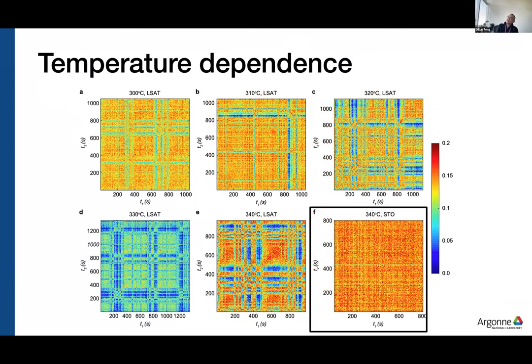And so if we look at the temperature dependence of these two-time correlation maps, you can see that, as you would expect, there's more fluctuations at higher temperature, okay? And to contrast that, I'm showing you the two-time correlation map for strontium cobalt oxide on the STO lattice parameter at 340. So to contrast the 340 at LSAT, which is right next to it, to the one that's on STO, you can see that the one at STO is essentially not moving.